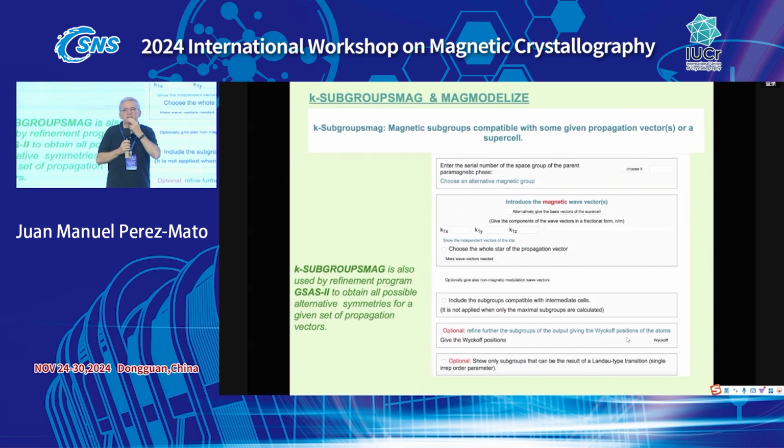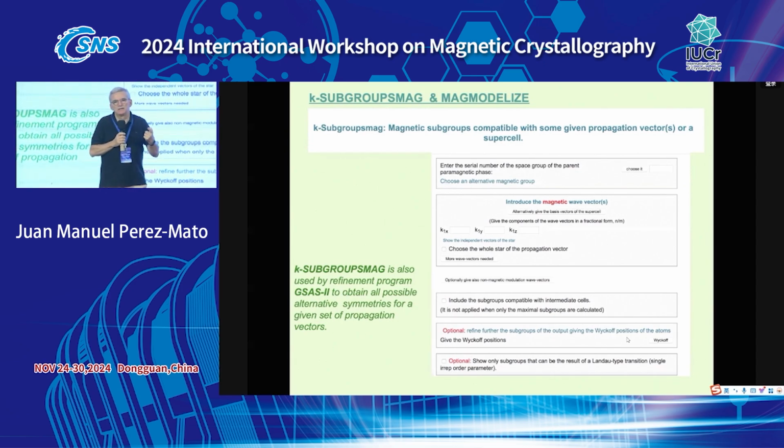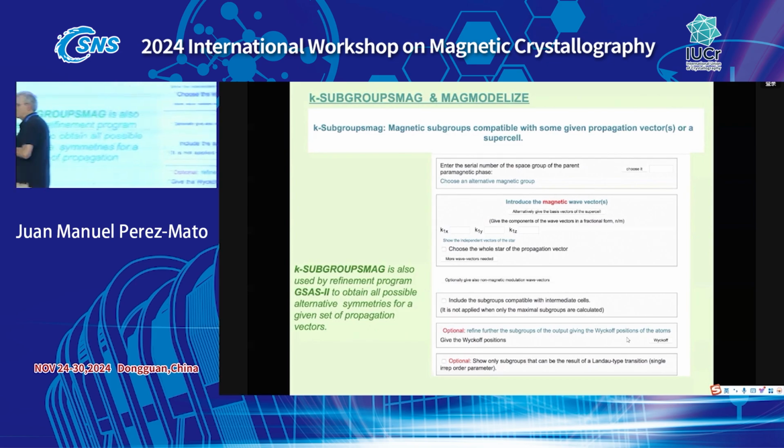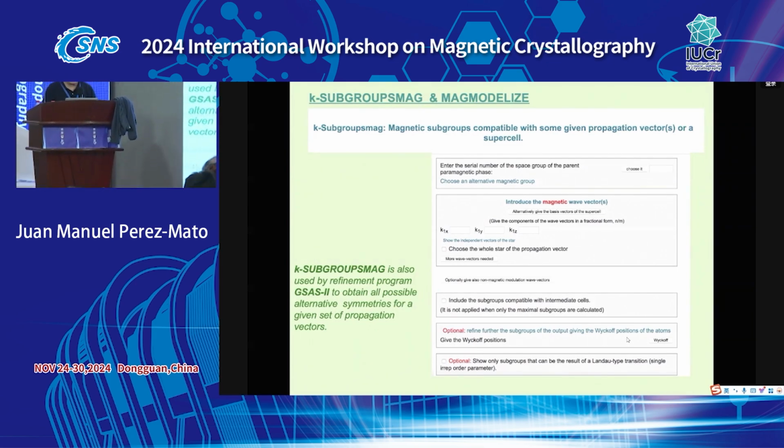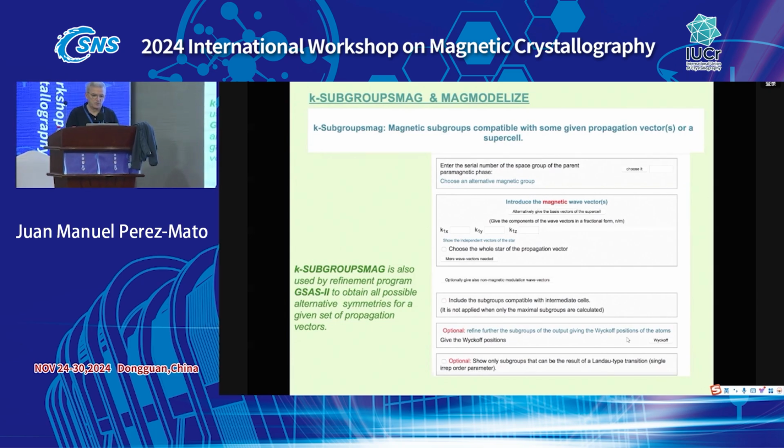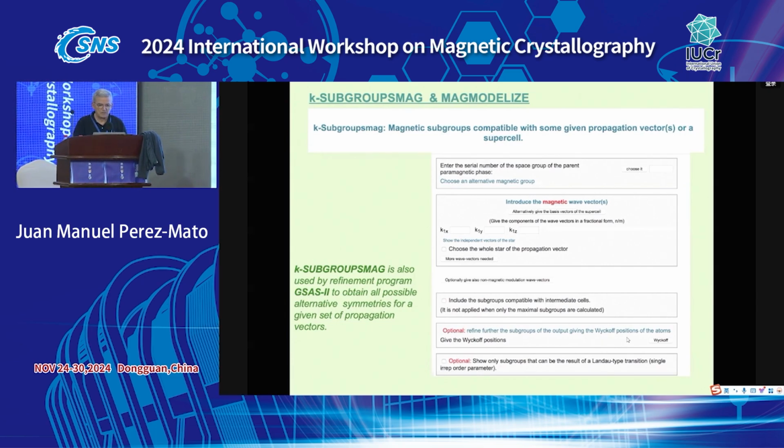By the way, if you are using powder diffraction, you will never be able to distinguish between structures where there are several k vectors which are symmetry related. If you have several wave vectors which are symmetry related, powder diffraction is not able to say whether it is a structure with a single wave vector, or all of the symmetry related wave vectors are involved. So in many cases the refinement will be equally good with the two models.